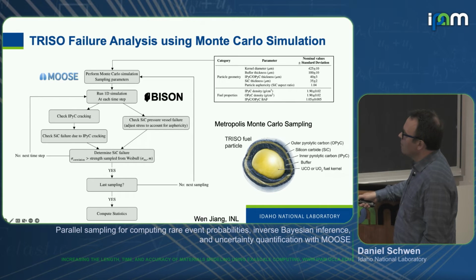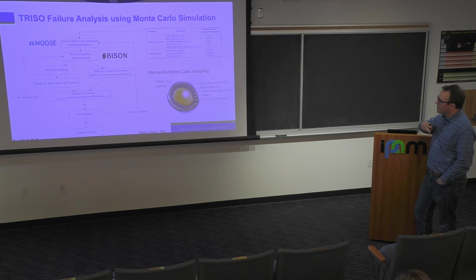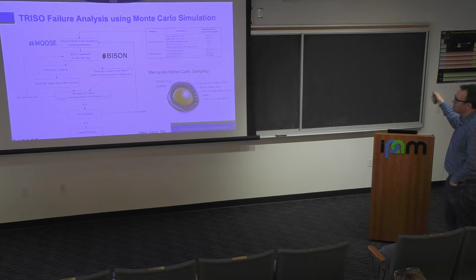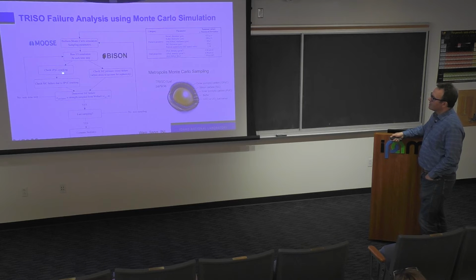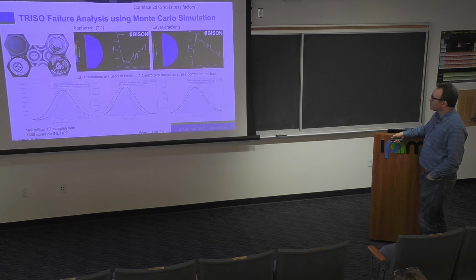And basically the Moose application runs, in his case, a 1D simulation of such a TRISO particle. You can assume this is spherically symmetric. We account for the asphericity by augmenting the stress in a clever way. And then while we run this 1D TRISO run over many days, weeks, months, or whatever, we can check, will we get cracking in the pyrolytic carbon layer, will we get the failure of the silicon carbide layer, and so on and so forth. And then we report back, did the particle fail or not, and compute statistics.